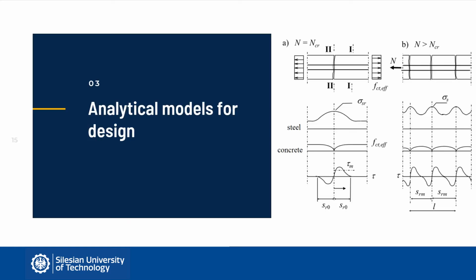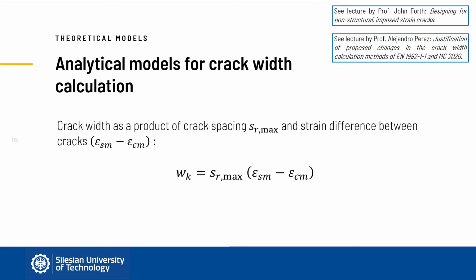The main aim of modeling of cracking is to provide robust design procedures for crack control. That is why before I move to the complex simulations of cracking, I would like to make a concise overview of the analytical approaches. In general, the analytical models for crack width calculation define the crack width as a product of crack spacing, or slipping length, and strain difference between the cracks, which is called crack-inducing strain.